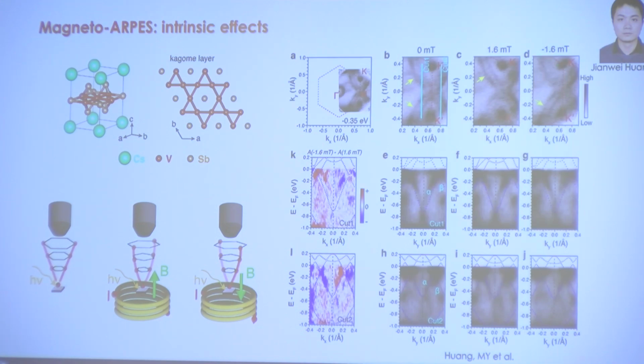To see that better, you can take 2 cuts and look at the energy dimension. Cut 1 is shown here, cut 2 is shown here. This is the crossing point, the end point between the top and bottom K and K prime. If you take the subtraction of these two, plus and minus field, which is shown here, you can see this is the part where the minus field is higher than the plus field, and this pattern is actually reversed when you go from this side of the zone boundary to this side. So this definitely tells us that this material has a very strong response to even a millitesla field. So I think this is very promising.